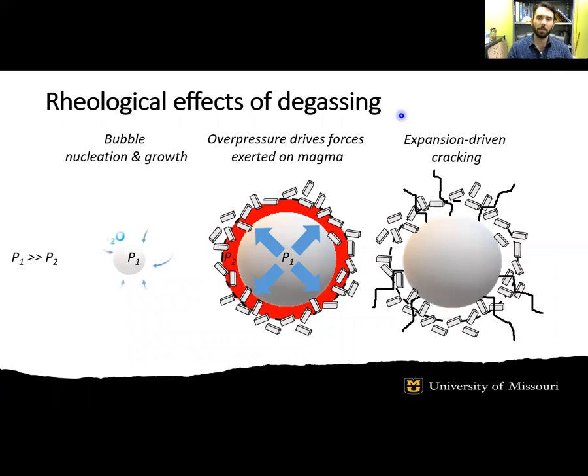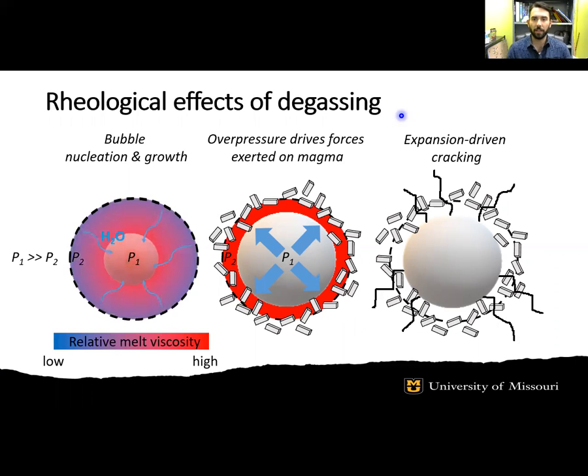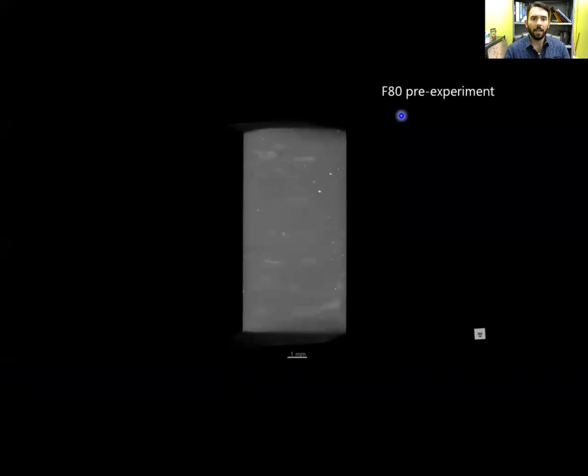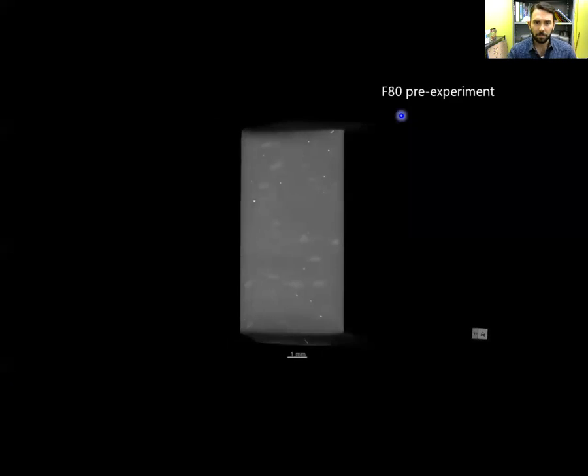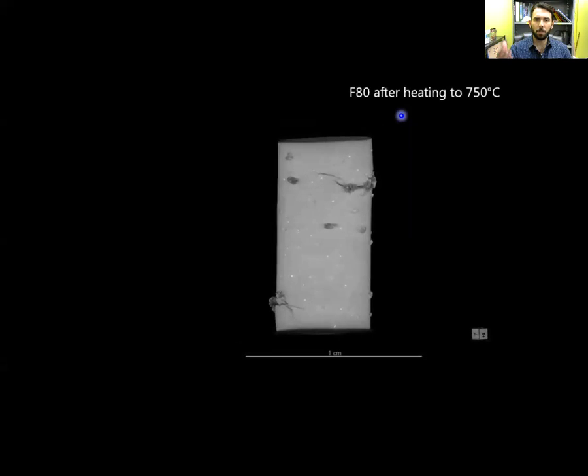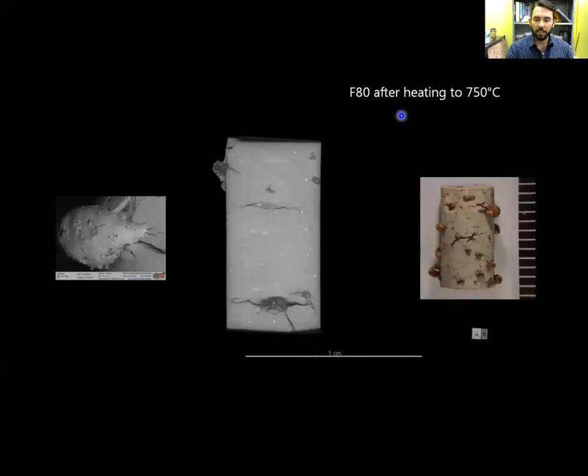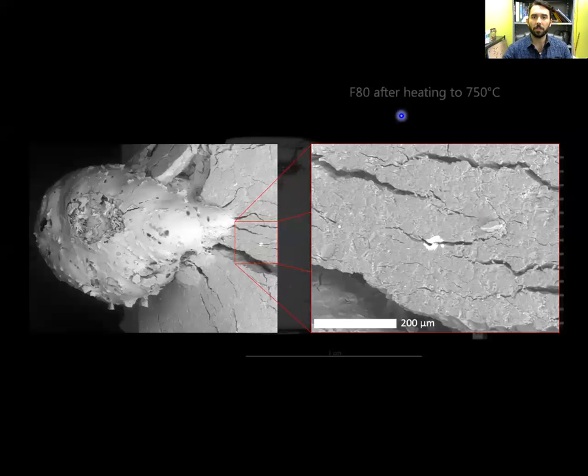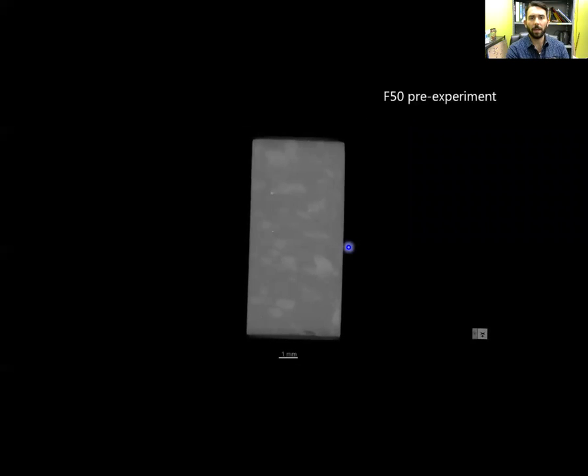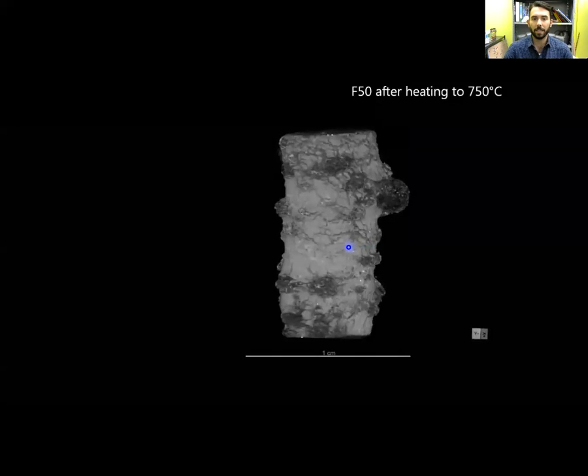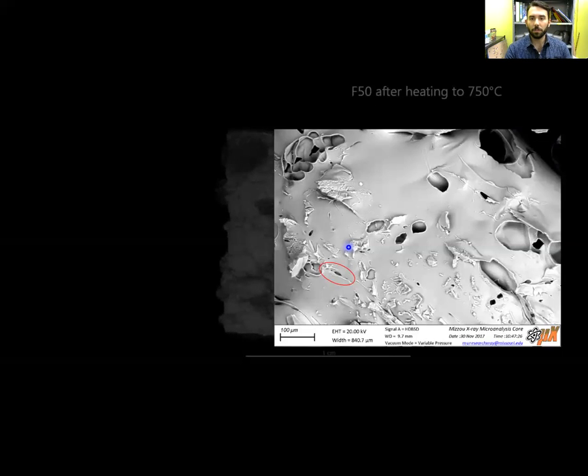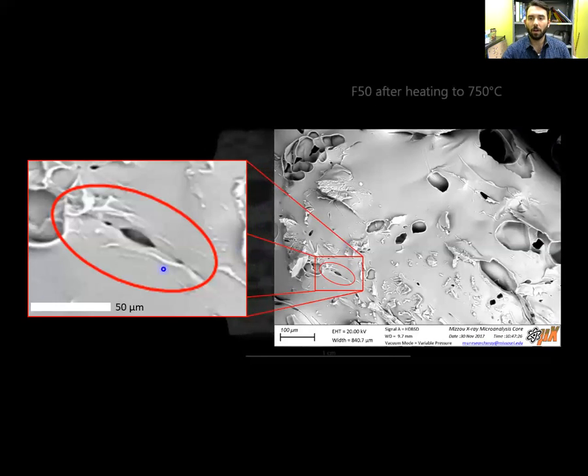And the reason is magmas become less compressible with increasing crystal fraction. Bubble expansion then leads to an increase in pressurization. SEM and tomography data show F80 was pervasively fractured and that samples preferentially preserved cracks within crystals, as we can see here. SEM data from F50 shows fractures in the melt are partially healed, implying that brittle and ductile deformation occurred contemporaneously above TG. This also further supports that crystal-rich domes are likely the healed remains of fractured, initially more hydrous magmas.